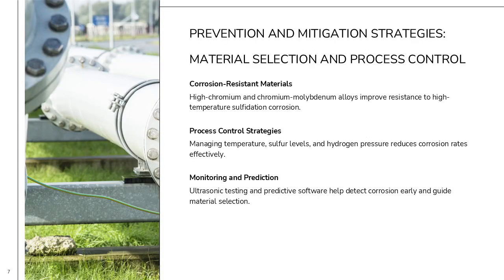Preventing high-temperature H₂S or H₂ corrosion requires a combination of material selection, process control, and monitoring. Using high chromium and chromium-molybdenum alloys, such as 304H, 310, and P91, provides enhanced resistance to sulfidation. These materials form more stable sulfide scales that resist spalling, reducing metal loss. Process control measures include managing operating temperatures, controlling sulfur and H₂S levels, and optimizing hydrogen partial pressure to minimize corrosion rates. Regular monitoring through techniques like ultrasonic testing is essential for detecting early signs of metal thinning and preventing unexpected failures. Advanced software tools, such as S-Compass, can assist in predicting corrosion behavior and selecting suitable materials for specific operating conditions. Implementing these strategies ensures the safe and efficient operation of hydroprocessing units.